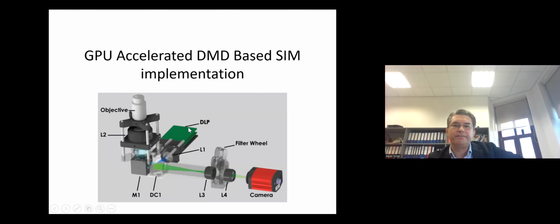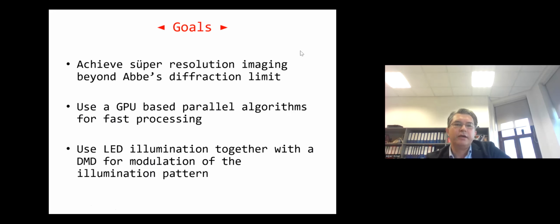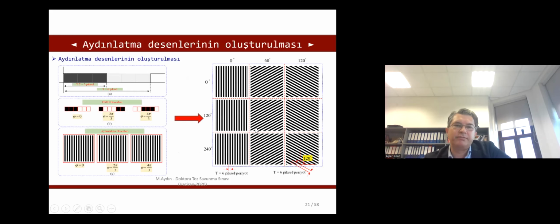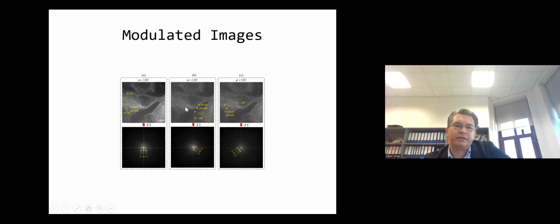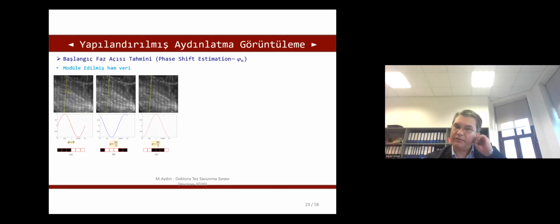So that's the idea, and it has been around for a long time, and we have worked on implementations of the SIM technique. What we are working on is to achieve this with LED illumination rather than laser illumination, using a commercially available DLP projector system, which has LED illumination, and we are also using GPU acceleration for post-processing to speed it up. So these were our goals: to achieve super resolution, a GPU-based algorithm, and LED illumination. We give these 9 patterns and obtain the modulated fluorescence images, and then recover the high resolution image from these 9 patterns using our GPU-based algorithm.